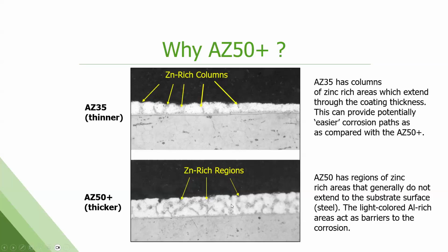On an AZ50 or higher product, you can see that the gray areas, the zinc-rich gray areas, very few of those actually make it down to the surface of the steel. And you've got a lot more aluminum surrounding it to protect it. So that's why we like to stay at the higher coating weights.